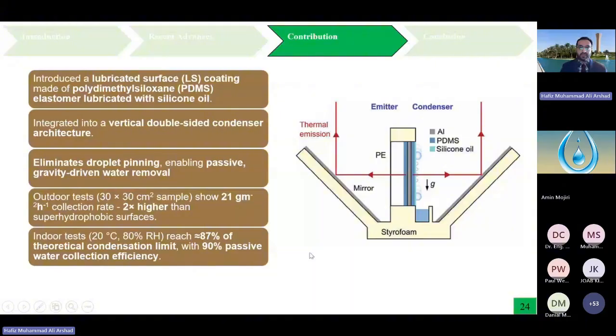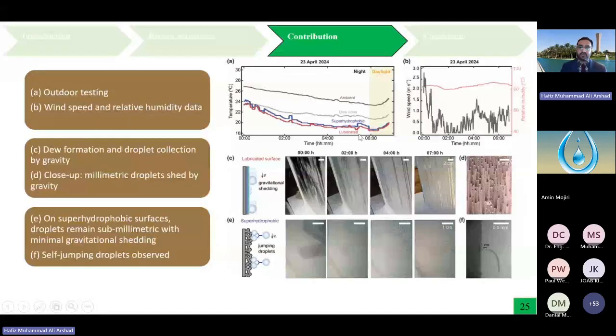So in figure C and E, we can see that once we have a lubricated surface, the gravitational shedding was really useful and we were able to collect a lot of water. But when we had super hydrophobic surfaces, the droplets were leaving the surface once they came together, with self-jumping droplets observed.